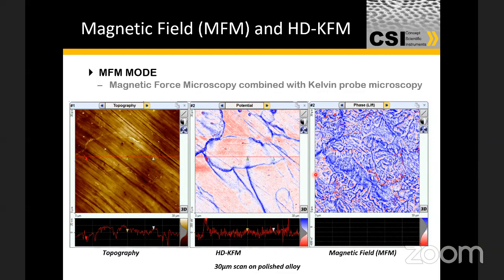The scope of making magnetic force microscopy measurements is relatively simplistic, in the sense that you're trying to interrogate the magnetic domains in your surface. The classic example is a magnetic tape, or a cassette tape. Its surface is very smooth, so the magnetic domains are not going to appear in the topography of the material. It'll have a certain potential difference also, which will reasonably follow the topography, if you have cracks and other things on the tape surface.